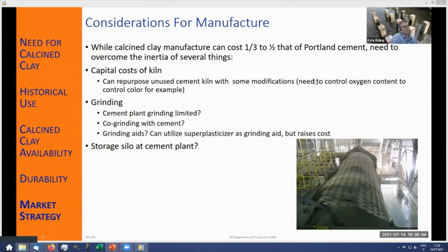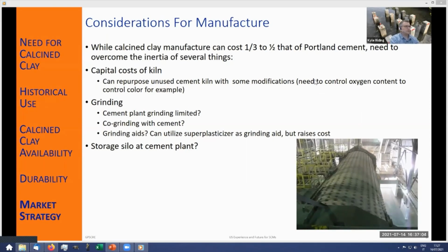Really your per unit cost can be one third to half that of Portland cement. But there's several things that you have to overcome since you're changing the system. There's capital costs that have to be adjusted for in order to be able to do this. And one is the cost of a kiln. If you already own a kiln to make Portland cement that's not being used, that reduces your cost significantly. Otherwise, it may be a $30 to $50 million investment to build a new kiln. And if you're going to adapt an existing kiln, you may have to make some modifications to control the oxygen content and control the color on it. But we know how to do this. It's just a matter of making some simple modifications to the plant. So there's the capital cost.